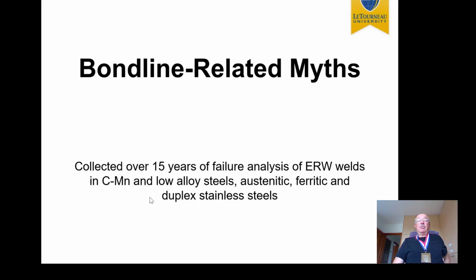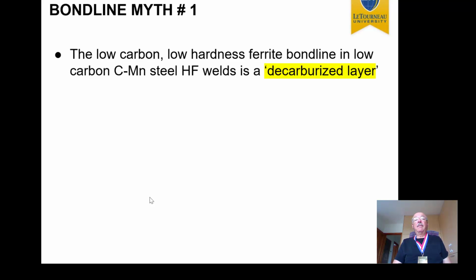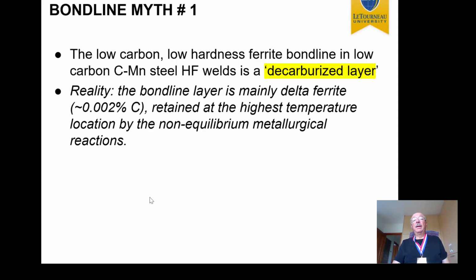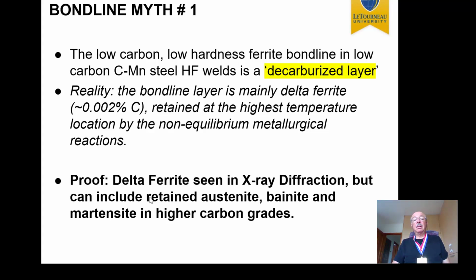So in these past 15 years, instead of concentrating on the shape, orientation and size of the bond line, people came up with lots of theories. And one myth is that the bond line, which has low carbon and low hardness, is a decarburized layer. In other words, the edges must have decarburized, and therefore they were retained as a decarb layer in the final weld. However, clearly, the bond line is never decarburized, but it is actually just delta ferrite, which was retained from the high temperature, as proven by X-ray diffraction. We clearly showed that it was only delta ferrite together with martensite and bainite in higher carbon grades.